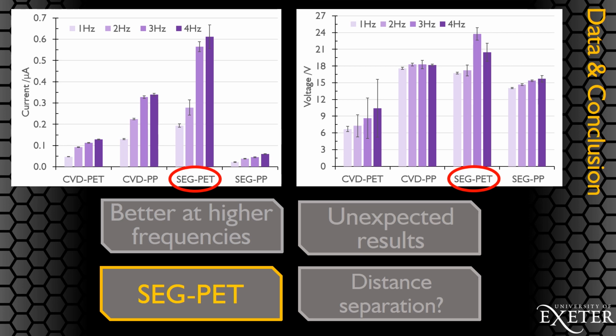When identifying the better performing configuration, it appears to be the shear exfoliated graphite on PET, with peak readings of 24 volts and 0.61 microamps. These values do seem to fall within the range that standard TENG devices have been reported before. However, it was expected that CVD would perform better than SEG.